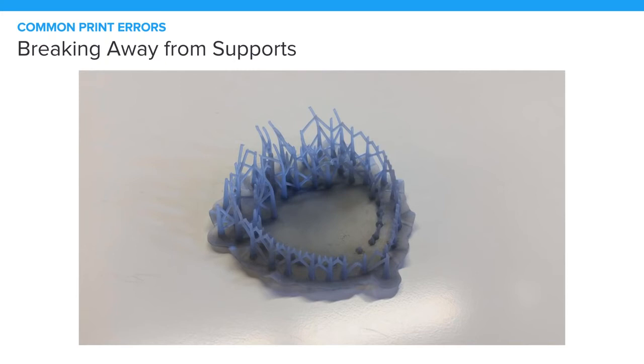So again, with this, try changing your settings back to default. Try increasing the touch point size. That might help. Try increasing the amount of supports. And then make sure your model follows the support rules. So, don't orient a long piece that's parallel to the build plate. Like I said before, you want to minimize the surface area per layer, and then try and make your model build off itself as much as possible.